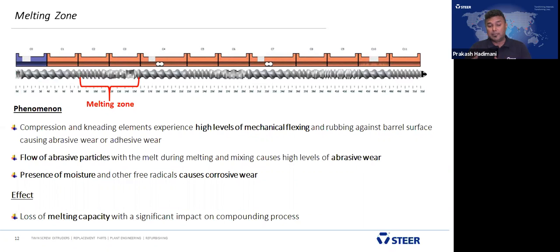We could move to the compression and melting zone. It includes the compression zone and the melting zone. What is the phenomenon? When the compression starts, the kneading elements experience a high level of mechanical flexing and start rubbing against the barrel surface, causing abrasive wear or adhesive wear. This phenomenon happens in the melting zone.